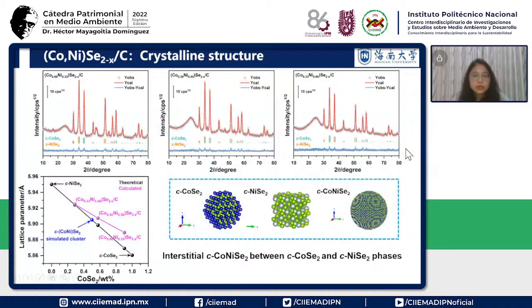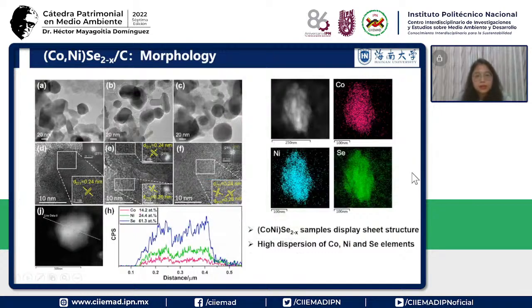And then we continue to investigate the crystal structure of this material. Based on the XRD analysis, the compounds are composed of cubic cobalt selenide and cubic nickel selenide. And also we found between these two phases there is an interstitial cubic cobalt nickel selenide. This is an interesting finding.